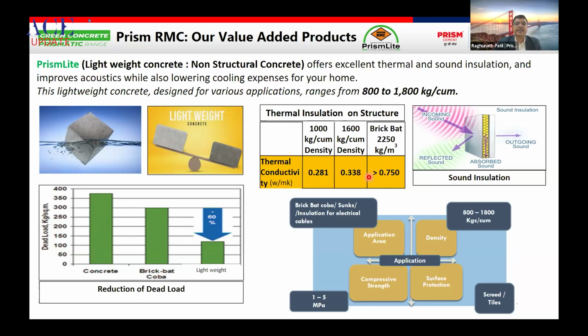The thermal conductivity is 0.75 watt per meter Kelvin for brick bat coba. Similarly, if you compare with lightweight concrete of 1000 density, it is just 0.281. It's just one third of the brick bat coba. This is also good for sound insulation.